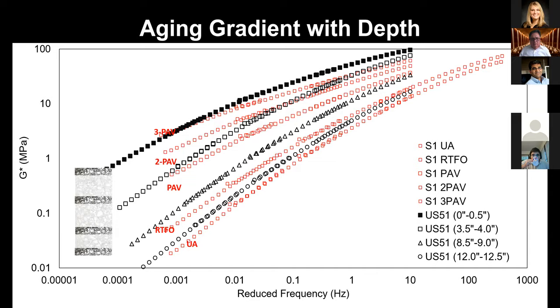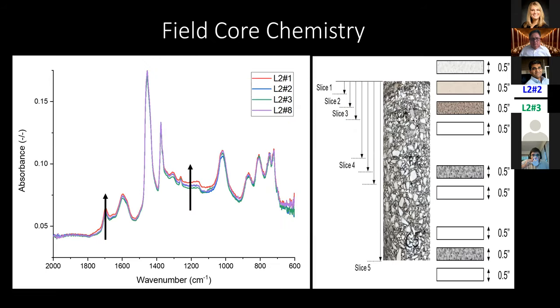our binder. I was surprised to see how much aging we were seeing throughout the depth of this core. I expected the surface to have the amount of aging and the long-term high aging that we saw, but I was surprised to see even at the depths of 3.5 and 8.5 inches, how much aging we were actually seeing at those depths. And that will be used to help determine the criteria as we move forward with how much laboratory aging we will want to use.